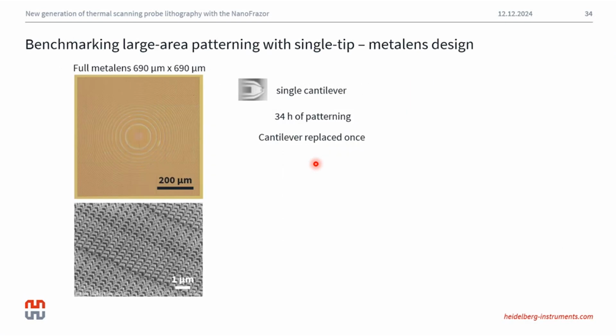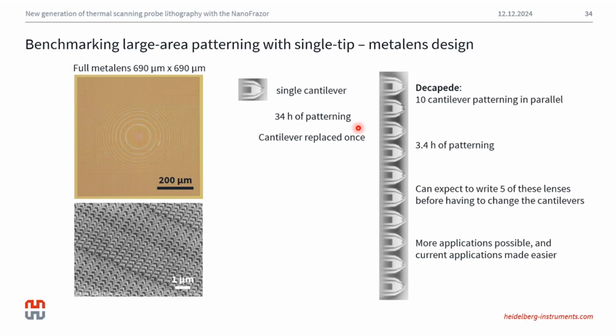So going back to our metal lens design, in order to achieve this large area 700 by 700 micrometer metal lens, we were doing the patterning over 34 hours, and we only replaced the cantilever once. So if you want to recreate this on a routine basis, you can imagine how patterning for 34 hours is not very practical. And this is why we've introduced our decapede module or multi-tip module.